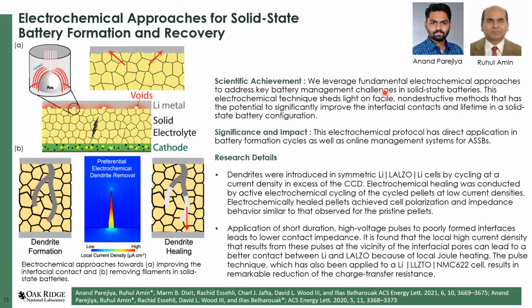So in addition to that, I just said that we think that solid state batteries are much safer than lithium ion batteries. However, even in solid state batteries, people have now realized that when you try to cycle a solid state battery, you're trying to take lithium from one side and move it to the other side. Sometimes you can form these things called dendrites. The lithium starts forming these filaments, which can penetrate even through a ceramic oxide. And that is bad because you can short circuit the positive electrode and the negative electrode if the dendrite goes through the solid electrolyte. And that is a cause of sudden release of energy.